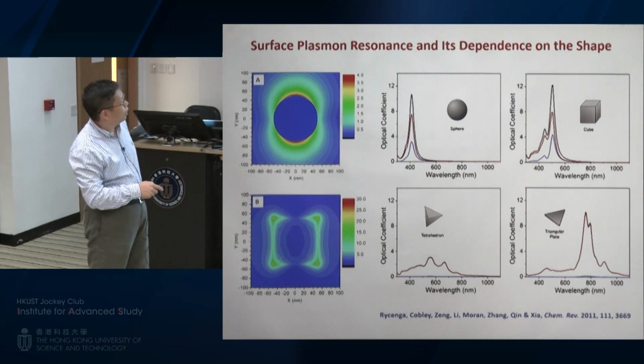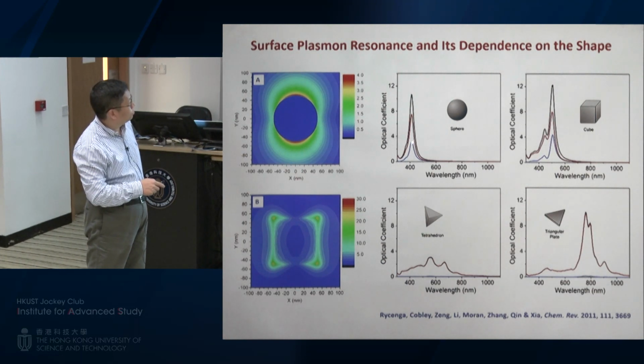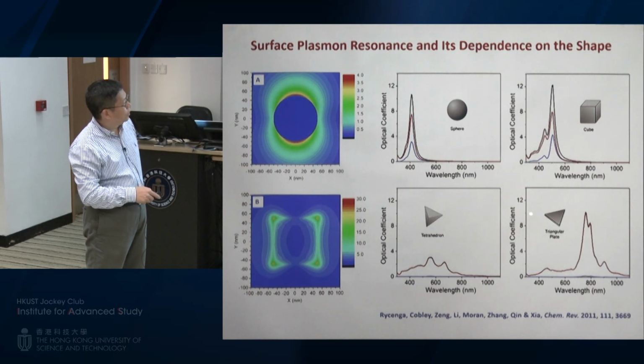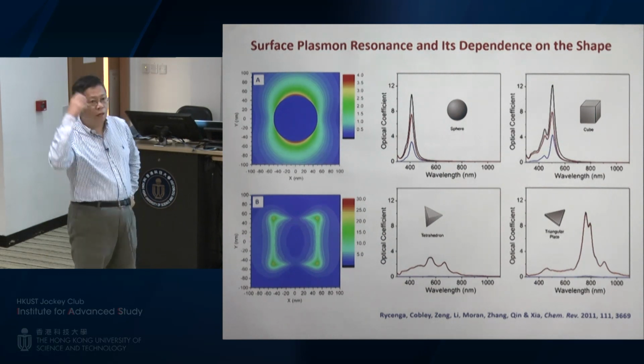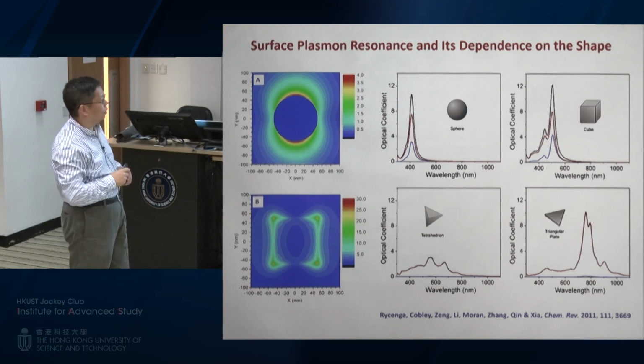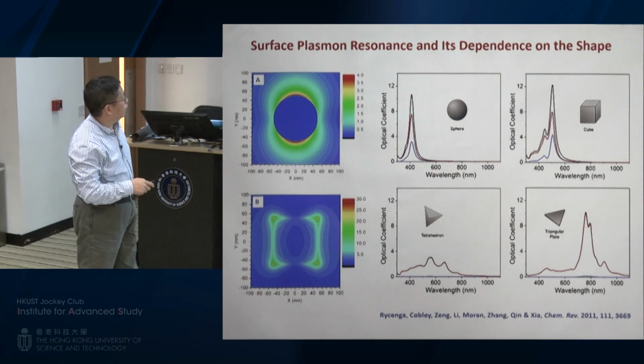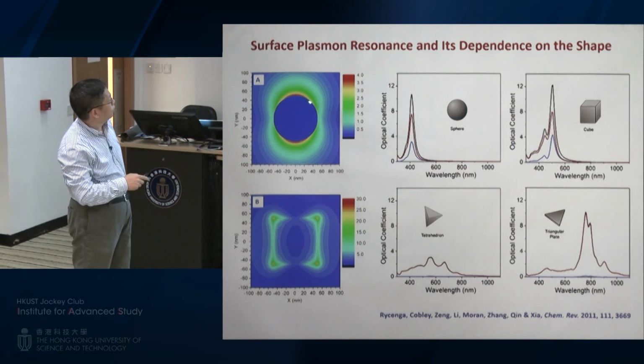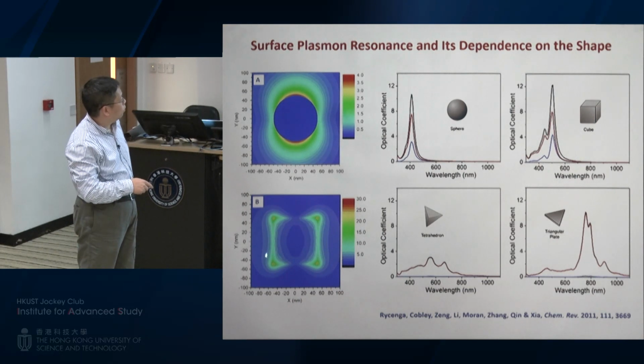You can also see the ratio of absorption to scattering. For the sphere, you still have quite some scattering component. But if you go to this thin plate, you don't have scattering anymore. It's essentially zero, and the major component is absorption. So you can see the dependence on the shape. For field enhancement, it is very clear: comparing sphere versus cube, at the corner sites you can have much stronger enhancement of the electric field. This is about 4 times, and this is about 30 times.